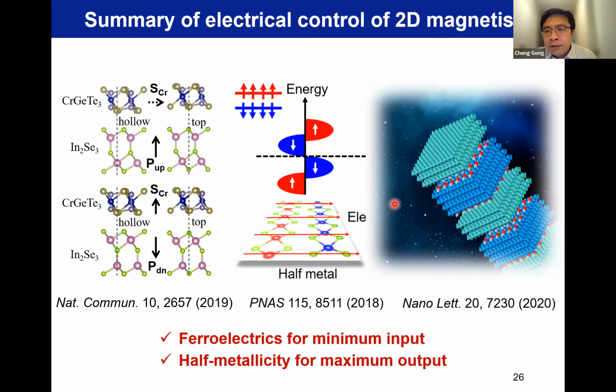So I will move on to two pieces of experiment we did on similar topics. It's not easy to fully demonstrate the half metallicity because there is always the depolarization process, and at finite temperature you also have the somewhat excitation of the spin minority carriers. So it's not easy to cleanly demonstrate 100% spin polarization. But anyhow, this at least provides a possible pathway.